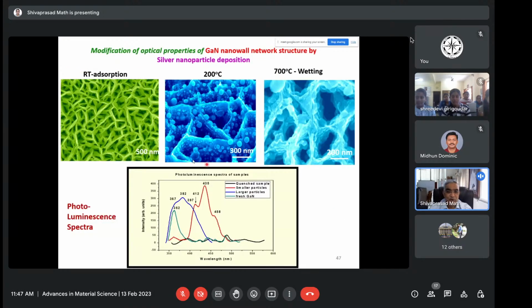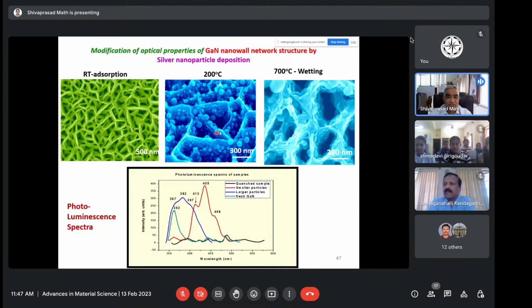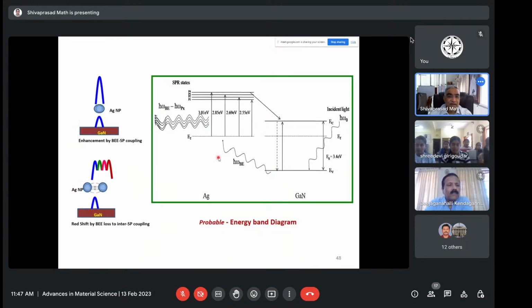Then we tried to understand it. What you see in this picture are gallium nitride nanowalls, and the spherical balls are the silver nanoparticles. The typical size of these silver nanoparticles is about 20 nanometers, and you see the edge of the wall is less than 5 nanometers. This became very important, I'll show you as we go along. Then we tried to model how the coupling of the band excitation with the plasmonic resonance will happen, so that a lot of light is released.